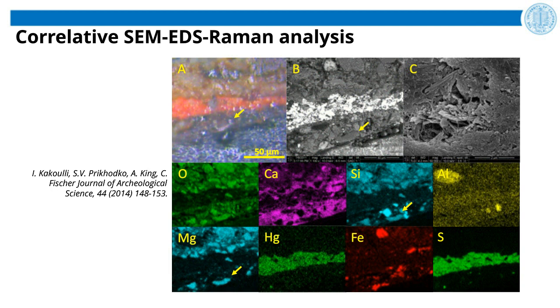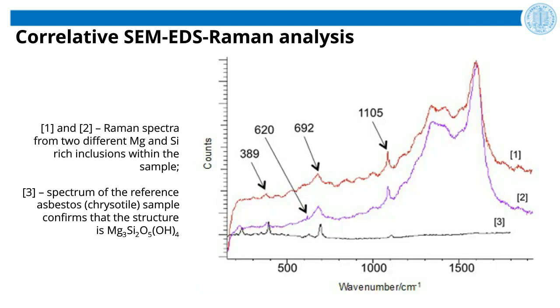Raman spectroscopy, here we see results taken with Raman, can give an unambiguous answer. Raman spectra number 1 and 2 are taken from two different inclusions rich with magnesium and silicon. Those spectra are compared to a reference asbestos chrysotile sample, confirming that our inclusions which are magnesium and silicon rich are indeed chrysotile.